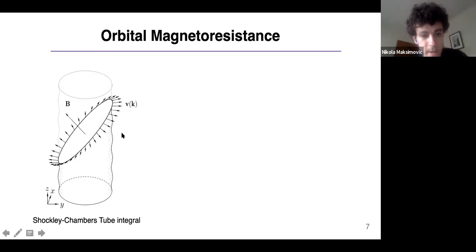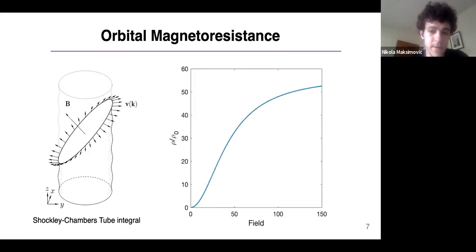The typical way to understand magnetoresistance, at least in what's called the relaxation time approximation, is you apply an electric field to the Fermi surface. And then when you apply a magnetic field in a perpendicular direction, the Fermi velocity of the quasi-particles will be averaged over these cyclotron orbits. And for most Fermi surfaces, the magnetoresistance that you get looks something like this. It's B squared at low fields and saturates at high fields. And there's a very, very narrow range of H linear dependence, if it's there at all. It's really more of a crossover regime between these two different extremes.